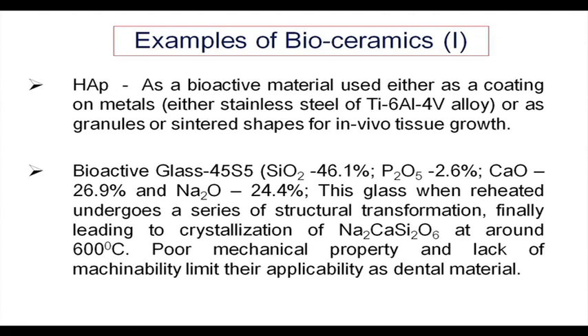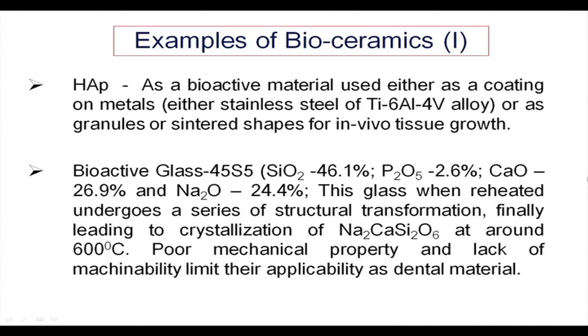Bioactive glass I mentioned already. The specific composition is given here. Silica is about 46%, phosphorus P2O5 is about 2.6%, calcium oxide is about 26.9%, and sodium oxide 24.4%. As all of us know, one of the major mineral constituents of bone is calcium or calcium oxide. So, all bioactive materials must contain some calcium oxide, and that is what is given here also in the glass. It contains a considerable amount of calcium oxide.